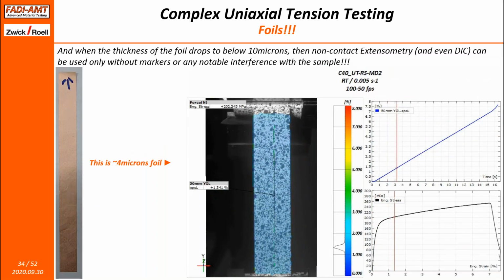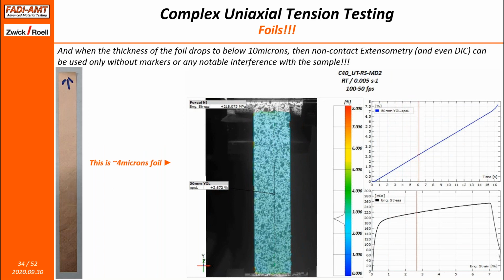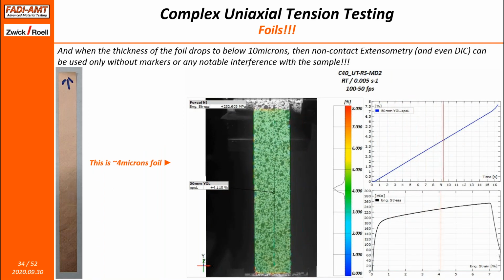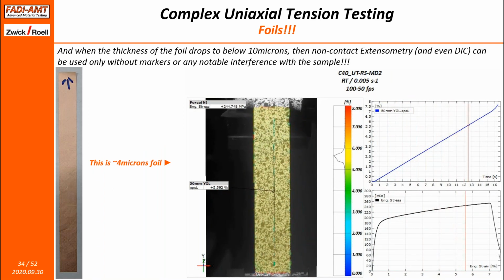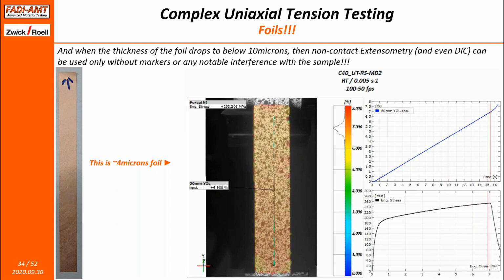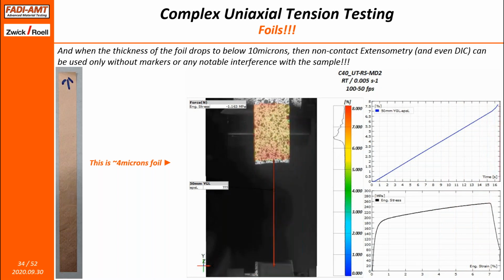Then we go to the extreme of the extreme. When the thickness of the foil drops below 10 microns, it's really, really difficult to use anything, because now your problem is not the type of technology. The difficulty is how you could use any type of extensometer, whether it's video, laser, or DIC, without damaging the sample while you're marking it. So here we say all technologies are comparable. It only depends on your preparation of the sample.